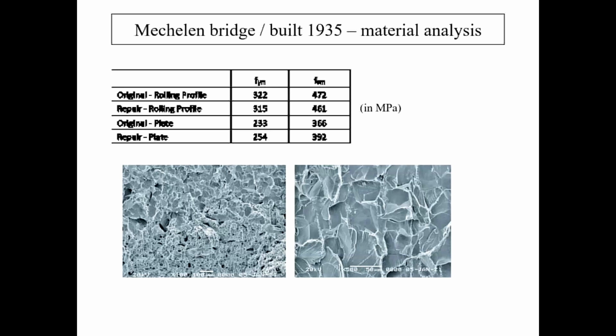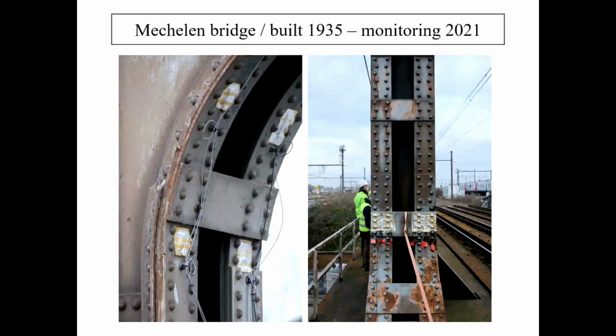The analysis of the fracture was entrusted to a specialized lab in the Netherlands, but it could not conclude if the cracks were either resulting from fracture, from fatigue, or from the blast loading of May 1940. Other analyses were performed, like the monitoring of the bridge with strain gauges. As you probably know, even with heavy loads, the magnitude of strains that can be registered are low on railway bridges, but they can be useful to calibrate numerical models.